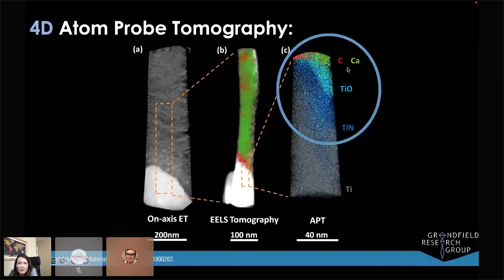What was interesting is we noted that titanium dioxide was on top of actually a nitride surface underneath, and this was due to our sample being laser modified in air.